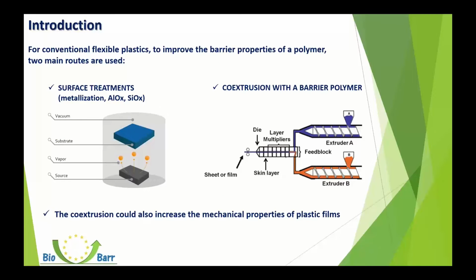Usually for conventional plastic, there are several techniques to improve barrier properties of a polymer. The main techniques are, for example, the use of surface treatments that consist in the application of a thin barrier layer by physical vapor deposition techniques, like, for example, the metallization, the AlOx treatment, or SiOx treatment. The conventional aluminum metallization is widely used in flexible packaging, for example, for polypropylene, that is widely used as a metallized film to improve the range of the food that can be packed with an improved barrier of this material.